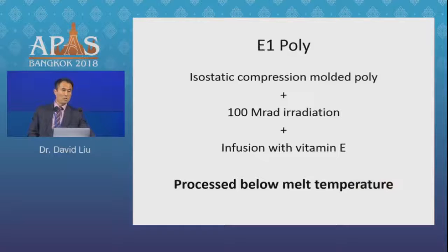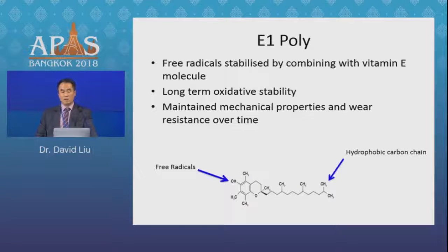The vitamin E basically quenches the polyethylene of the free radicals. After the irradiation process, the vitamin E is infused, and this negates the necessity for trying to rid the polyethylene of the free radicals by heating it. So you no longer have to heat the polyethylene to deal with the free radicals. And how does it do that? The vitamin E molecule binds the free radicals, thus not making them available to the oxidation process once it's implanted or removed from its vacuum seal. So the free radicals are still present within the polyethylene, you haven't got rid of them, they're just no longer available for the oxidation process. But the advantage is you no longer have to heat the polyethylene, which compromises its mechanical strength, and so you maintain the mechanical properties and the wear resistance over time.